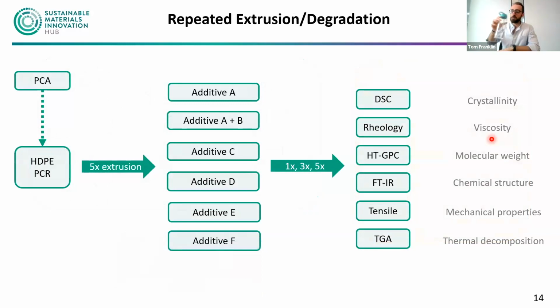Our workflow was to take a resin from our principal component analysis and subject that to 5 rounds of extrusion with each of these different additive groupings, and then characterize select extrusion cycles from these groupings with a whole suite of different characterization methods that we have in the lab. And again, you can see the list of the kind of broad information we can get from each technique, some covering the properties, some covering more of the base chemical structure, but all really looking at the effects of degradation on our polymer, both with and without additives, seeing what the effect of these additives is.